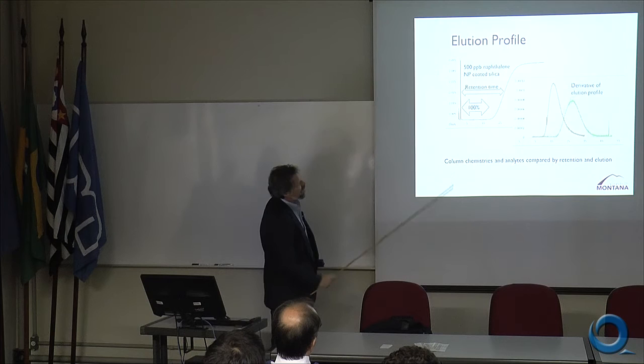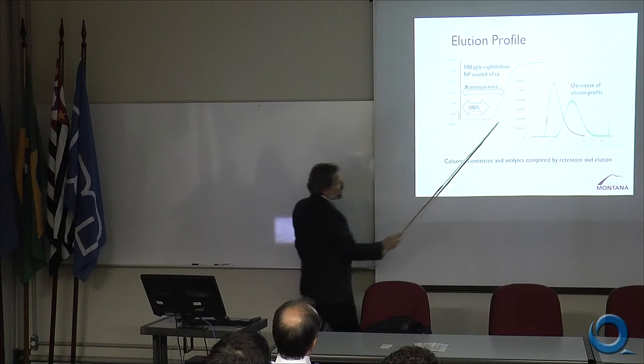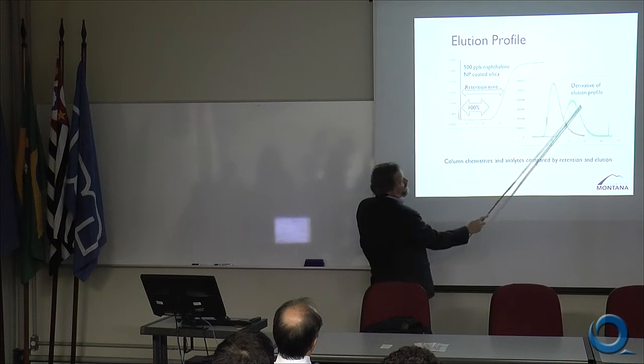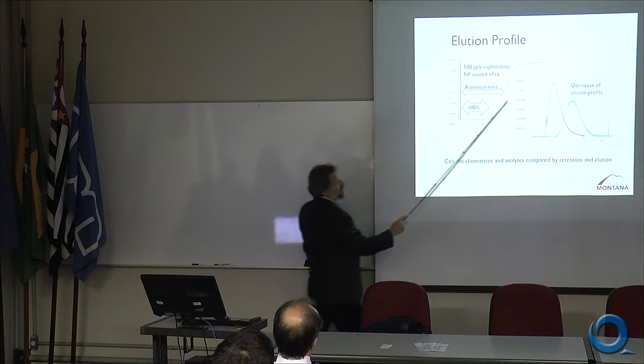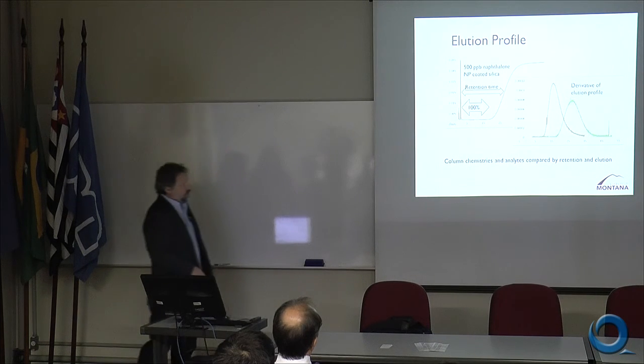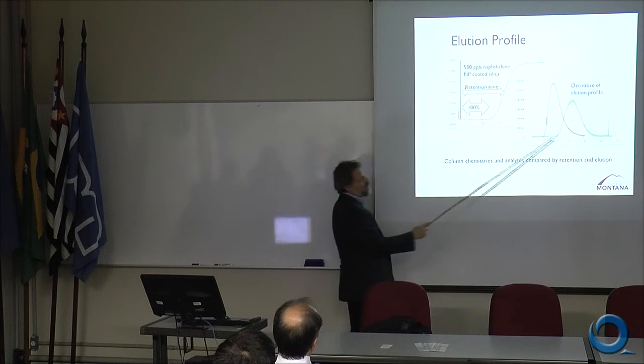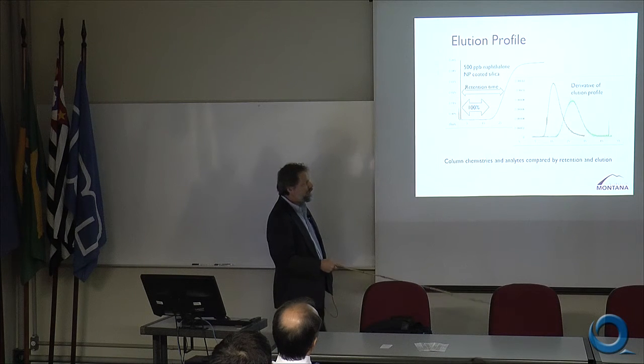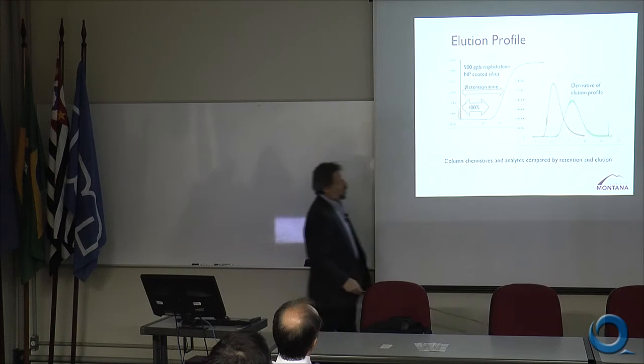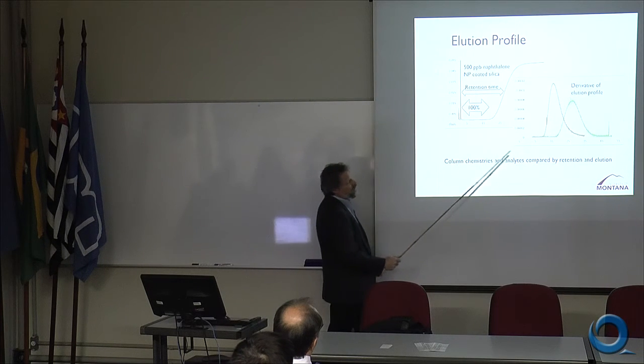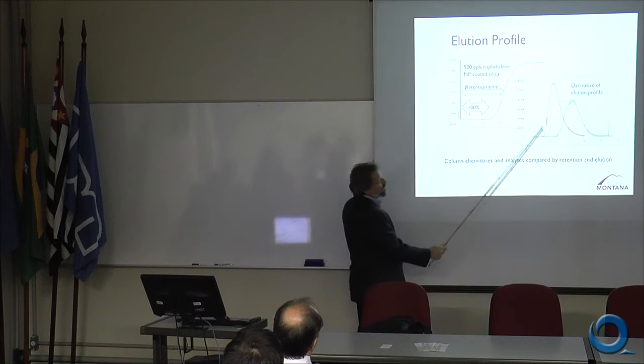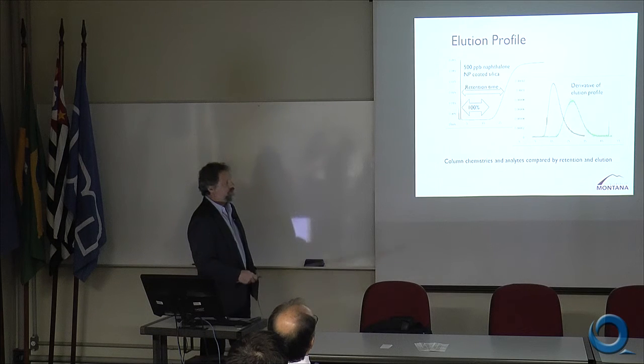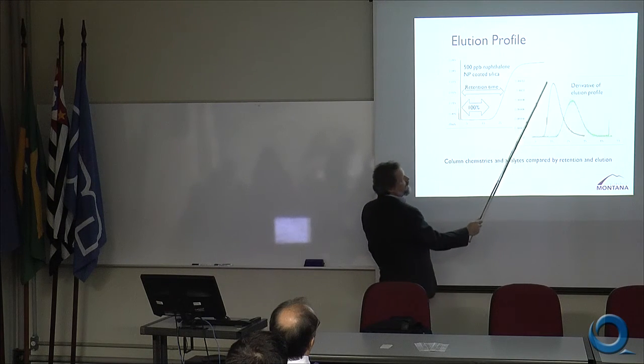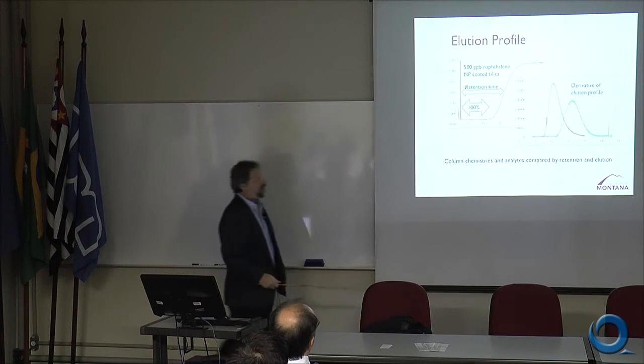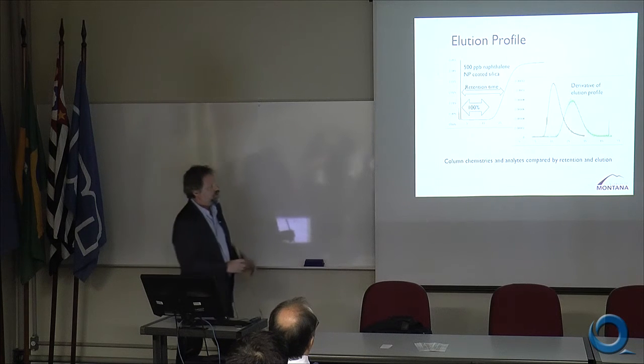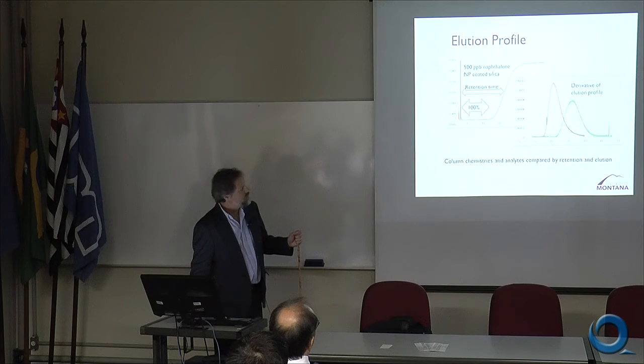So I apologize for the mix-up in the colors, but if we take the first derivative of this orange trace here, what we get is this green peak. And the maximum value in this peak comes at the inflection point of that front. So this is what you would expect to see if you had injected it as in chromatography as a peak. You'd see a peak like this, and this is just a representation of what the chromatography would look like. What we can do then, by collecting these fronts, taking the derivative, you get a lot more noise, of course, when you take the derivative, so we have to smooth out the signal. But then we can look at different retention times and retention factors as a way to evaluate different surfaces, different materials, and utility for different types of molecules and analytes.